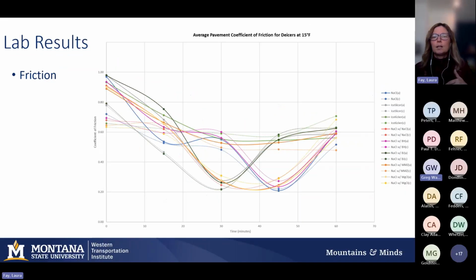Now, we also did the same testing at 15 degrees. And what you see here is another interesting trend where you have a start of surface friction being fairly high. But in this test, it was grouped by pavement type. So the upper values at time 0 for the pavement are asphalt, and the lower friction values at time 0 are concrete. And then as you apply the product, again, friction drops for the asphalt, but for concrete, many of the products